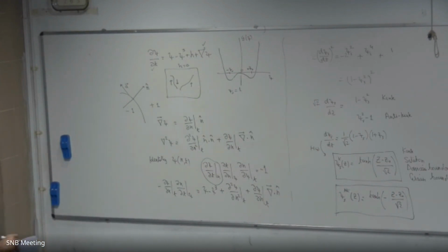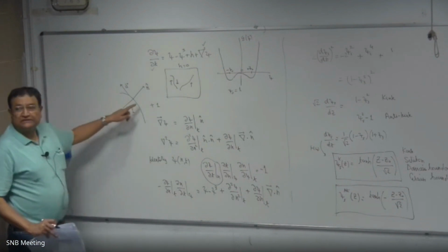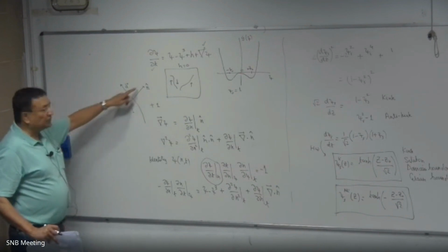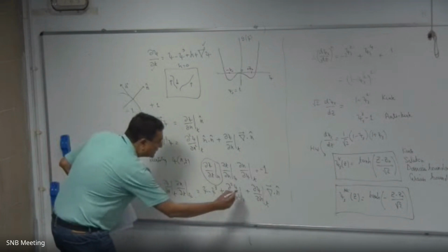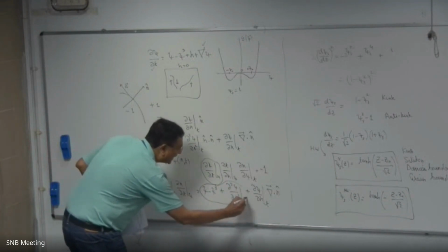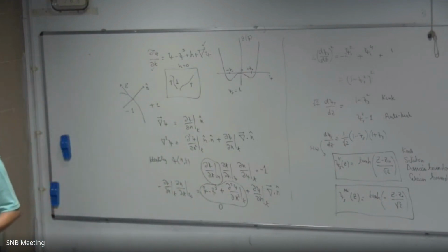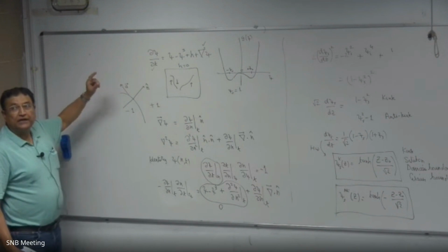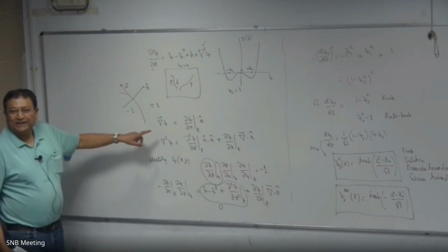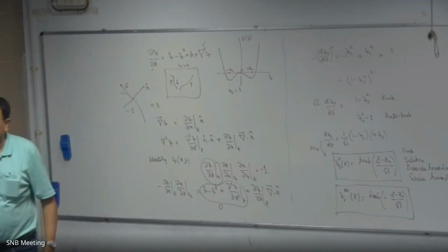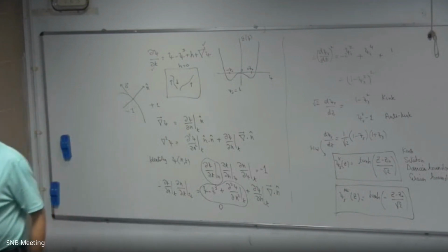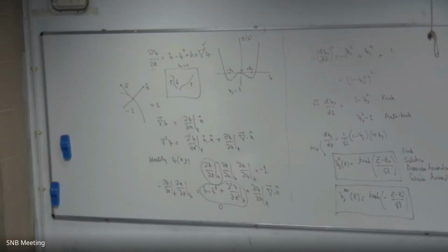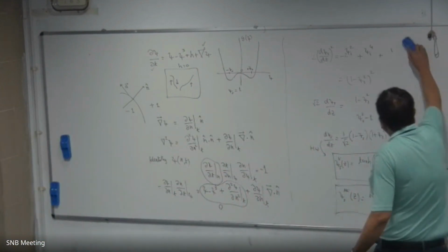What next? Next thing is to realize that at late times the interfaces are locally equilibrated. So you can assume that along the n direction you're actually a kink. And if you're a kink, then you know that this guy is identically 0 because it's just the solution of the kink. That's an important assumption here. Let me make it clear. It can only be an actual kink if it's a flat interface. At late times the curvature is sufficiently low that you can assume along the normal direction it's a kink. Kink means it satisfies the kink equation, and that's just that equation, which is why I wrote it in these curvilinear coordinates in the first place. And that actually gives me the equation which I was targeting.